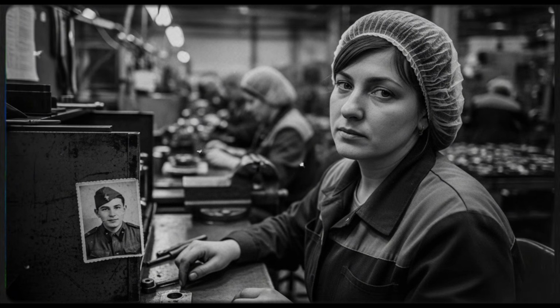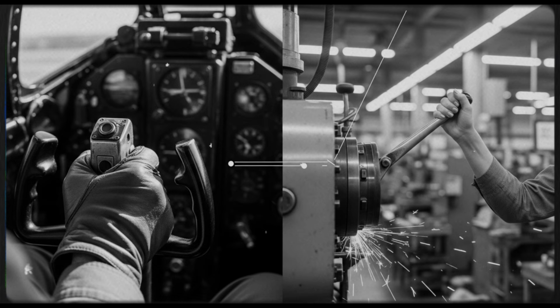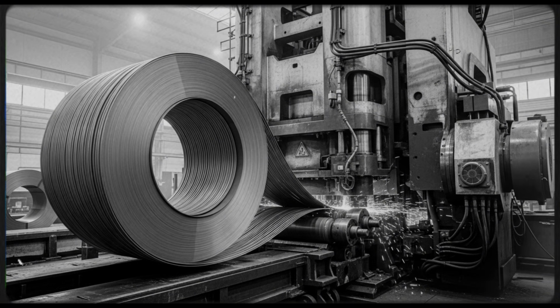They carefully reduced the thickness from 5/10,000ths of an inch to 3, then down to 2. The rings continued to perform. They were balancing on a knife's edge. Too thick and the nation's chrome supply would be exhausted. Too thin and the plating would wear away prematurely in combat. They had to discover the absolute minimum effective thickness.